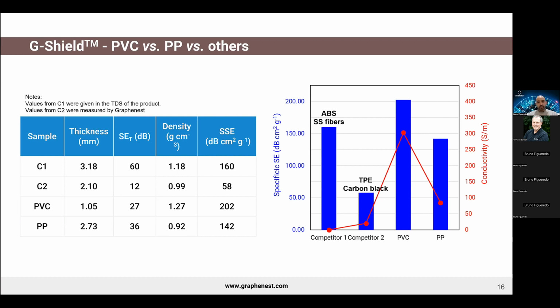To make a proper assessment, we decided to plot two figures of merit. The first one, in blue bars, is the specific shielding effectiveness, which was determined by dividing the shielding effectiveness by the density and multiplying it by the thickness. And the other figure of merit was the surface conductivity.